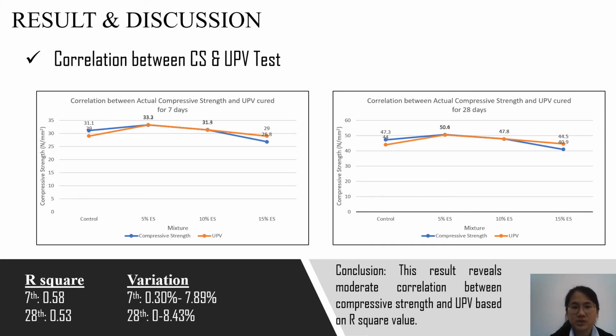In this research, we also studied the correlation between compressive strength and UPV test. From the result, we can know that the variation lies between 0 to 8.43% for both 7 days and 28 days. From the R-square obtained from this analysis, we can know the value falls between 0.53 to 0.58. This result reveals the moderate correlation between compressive strength and UPV test.